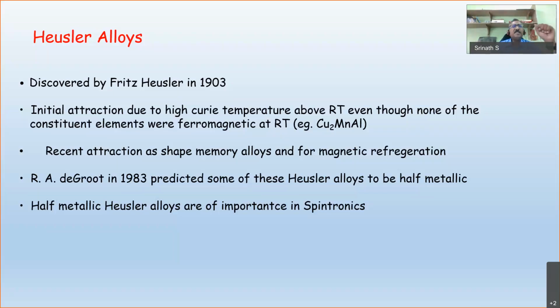But for the first time in 1903, Heusler showed that starting with non-magnetic elements, like copper, manganese, and aluminum, he made this compound Cu2MnAl. None of them are ferromagnets. But this alloy was found to be ferromagnetic, with a Tc above room temperature and also large magnetization. This opened up the gates to many more materials, because you don't need a constituent element to be ferromagnetic to make a ferromagnetic material. That is why this class of materials is named after this scientist, Heusler: Heusler materials, Heusler alloys.